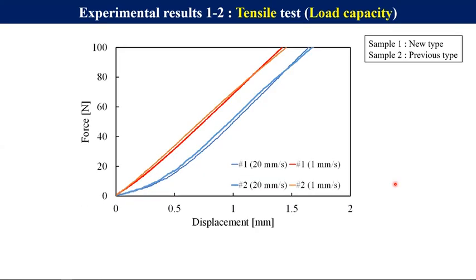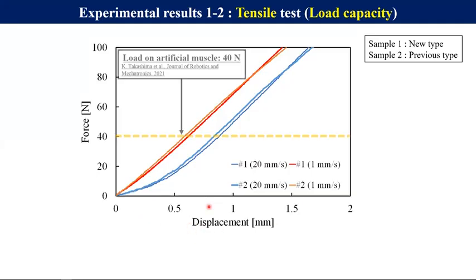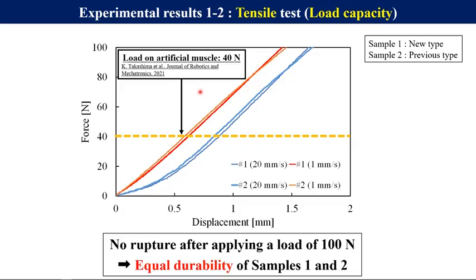This is the experimental result of the tensile test of load capacity. The vertical axis of this graph shows the force, and the horizontal axis shows the displacement. And I'd like to draw your attention to this yellow line first. According to the previous study, when an internal pressure of 0.1 megapascal was applied to an artificial rubber muscle, the extension force generated was around 40 Newton. And you can see that both samples 1 and 2 were confirmed to be able to withstand a 100 Newton load with no rupture. So from these results, we found that the durability of samples 1 and 2 were equivalent.